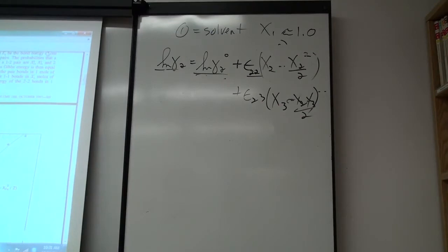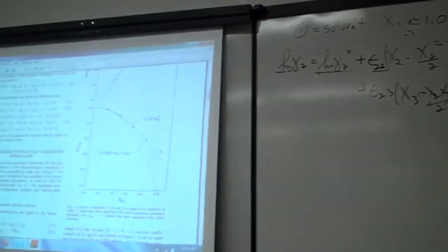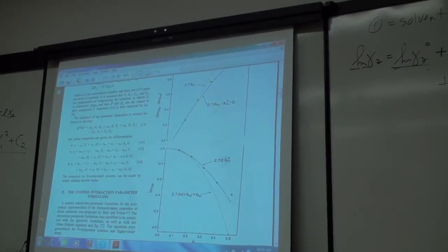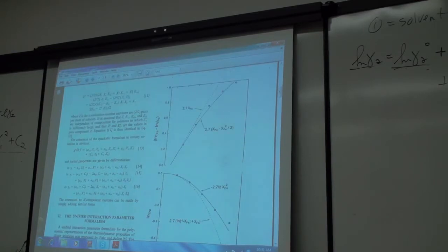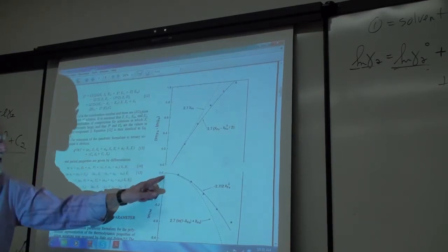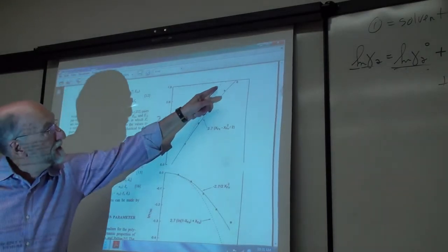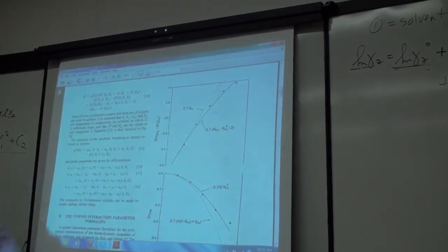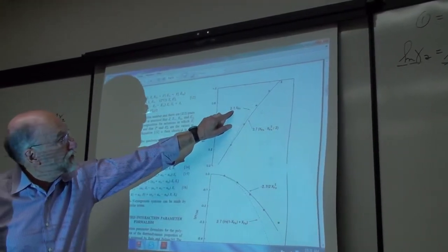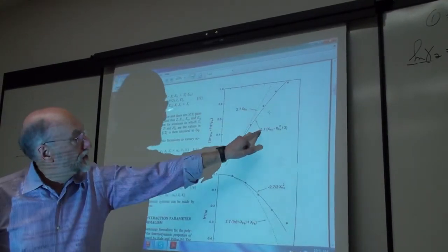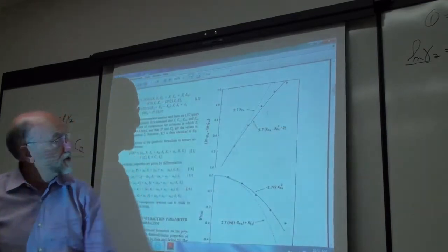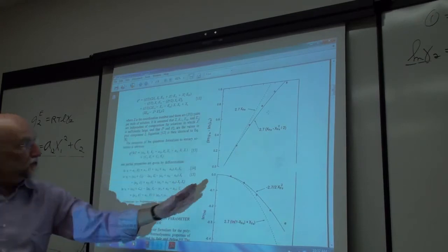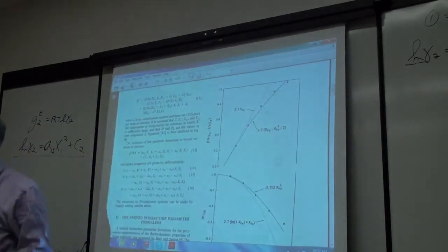You can see this is the iron-nickel solutions. So these are nickel solutions where iron now is the dilute component. Going down to infinite dilution, Wagner's formalism follows this line here. So you see the limiting slope is of course the same. The dashed line, this is the line where this epsilon 2 was 2.7, so that's the first term. This is the same term, 2.7 x minus x squared over 2. So of course the two become the same as x approaches 0, but as x deviates from 0, this follows the experimental points and Wagner's line goes off.